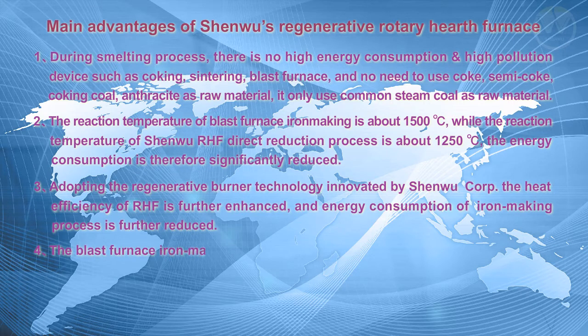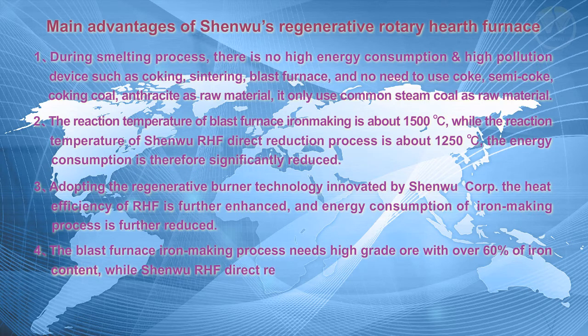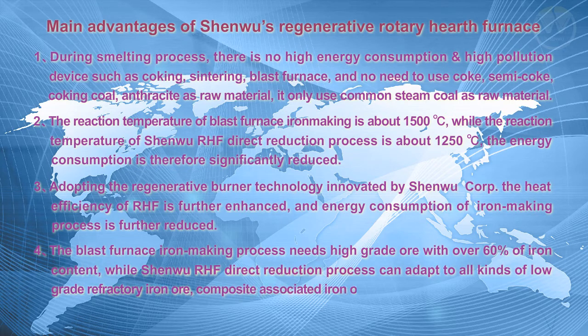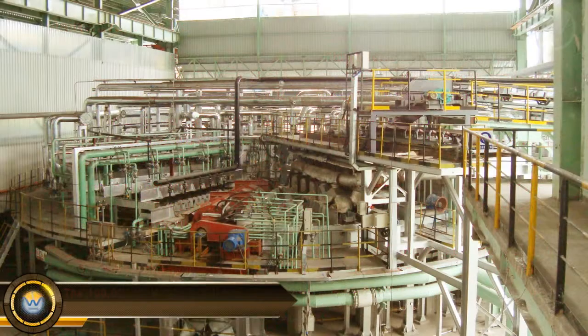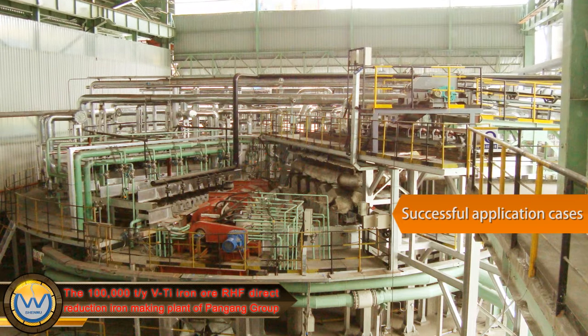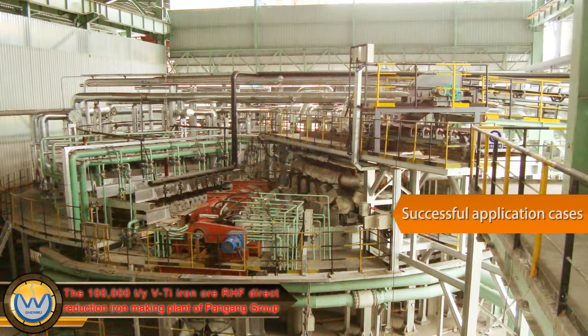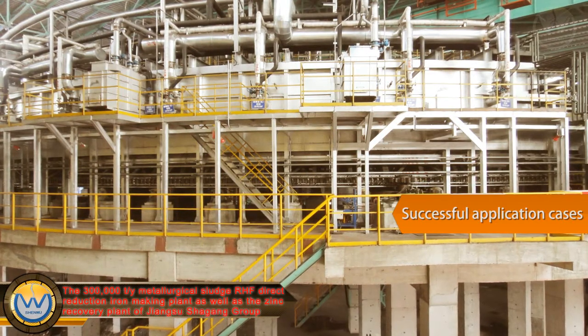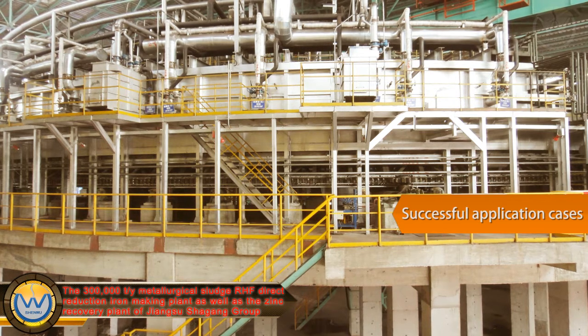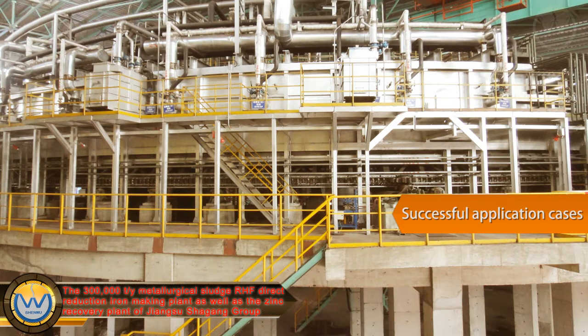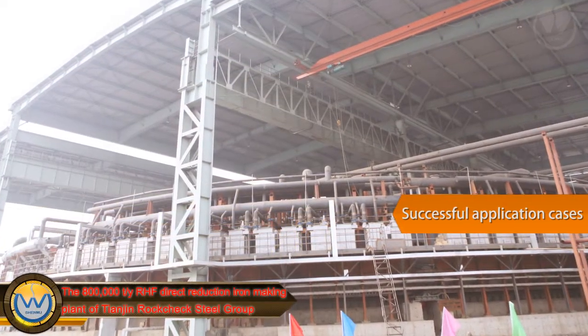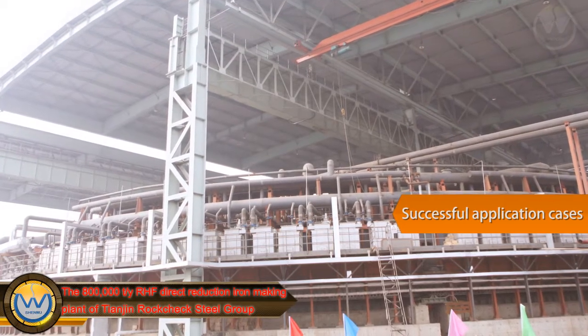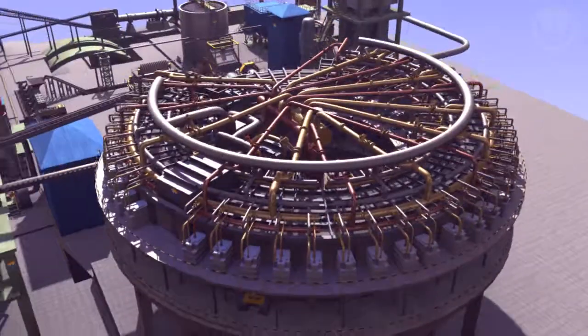4. The blast furnace iron-making process needs high-grade ore with over 60% of iron content, while Shenwu RHF direct reduction process can adapt to all kinds of low-grade refractory iron ore, composite-associated iron ore, lateritic nickel ore, and iron-bearing solid waste of the non-ferrous metallurgical industry. The 100,000 ton per year V-Ti iron ore RHF direct reduction iron making plant of Pangang Group, the 300,000 tons per year metallurgical sludge RHF direct reduction iron making plant, as well as the zinc recovery plant of Jiangsu Shagang Group, and the 800,000 ton per year RHF direct reduction iron making plant of Tianjin Rockcheck Steel Group, all of these have witnessed the success of the technology.